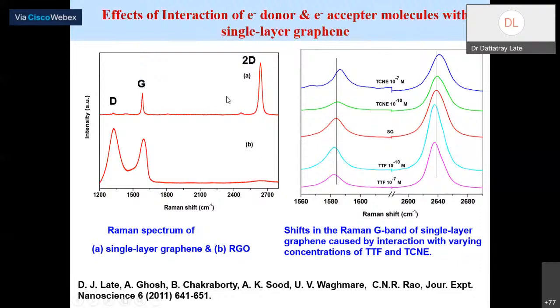Sample number 1 here, A, is pristine single layer graphene. You can see here the D band. Again, here a slight small D band, because of small defects in that graphene sheet. And this is the G band, which appears because of the stretching of the carbon-carbon bond. And this is the 2D band, a very nice 2D band. The intensity of the 2D band is more than the G band. This clearly indicates this is a monolayer of graphene.